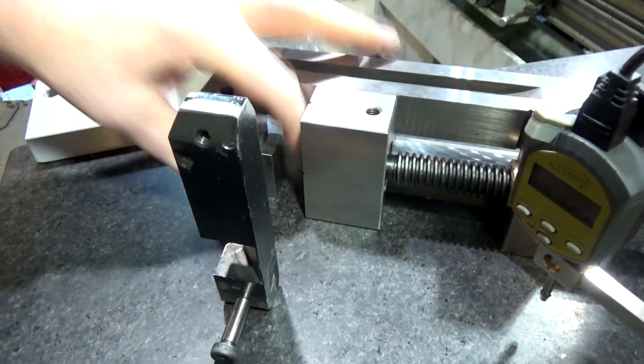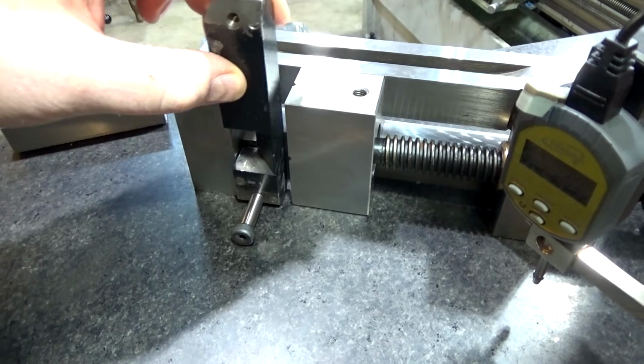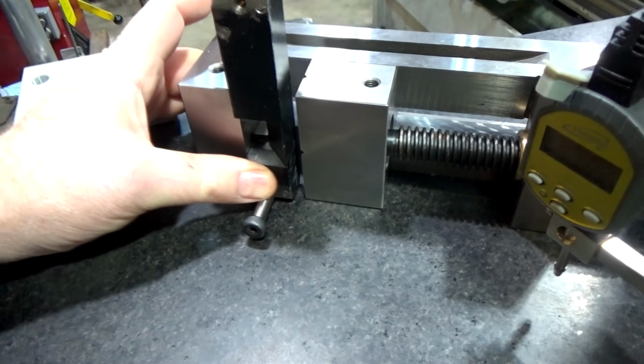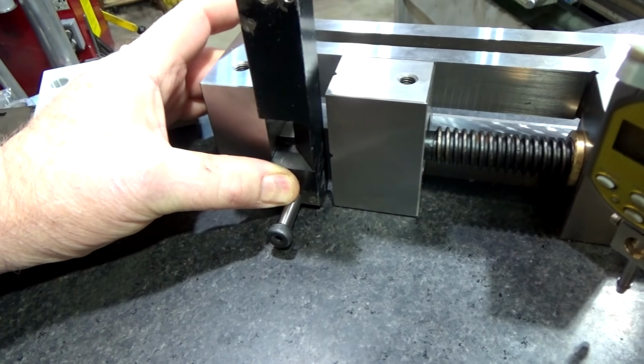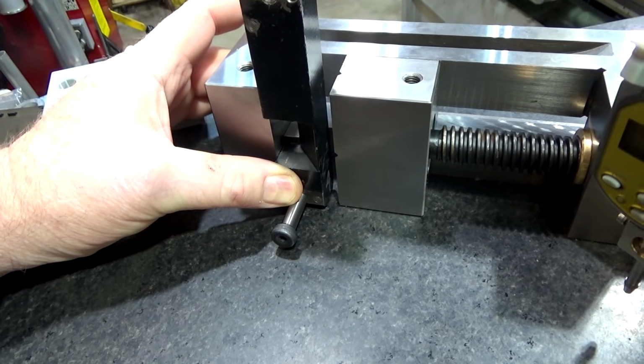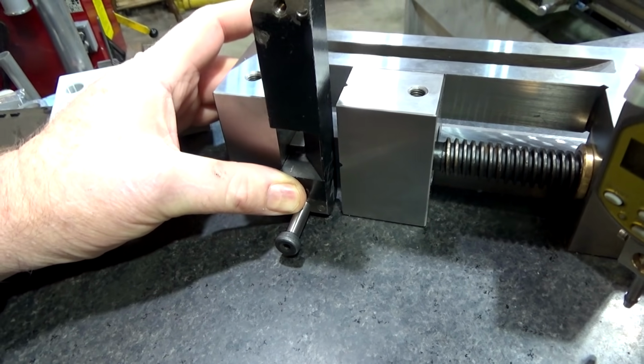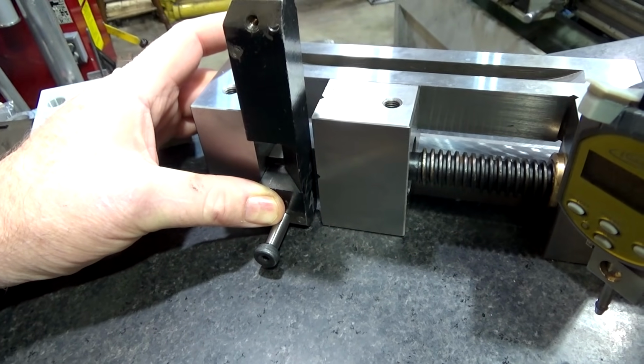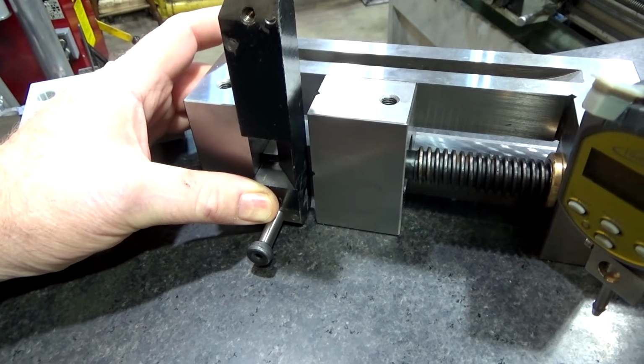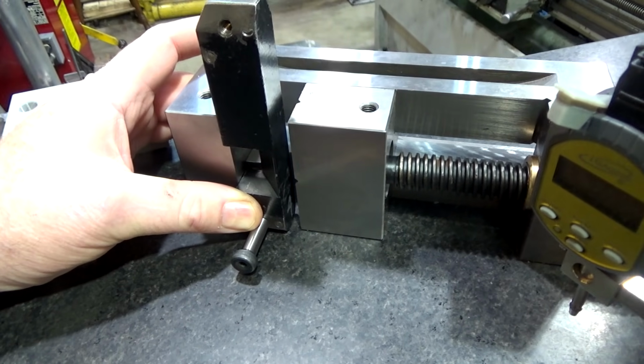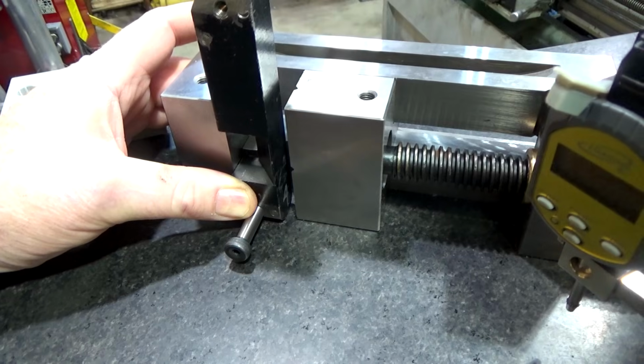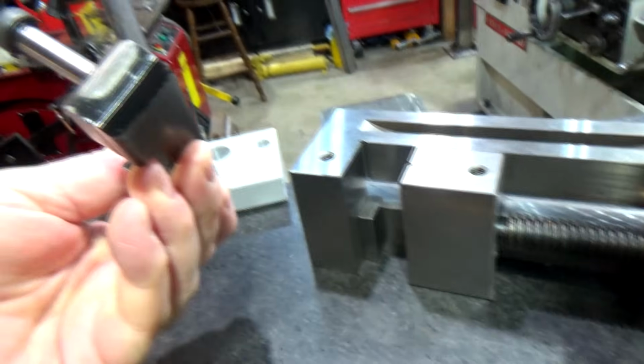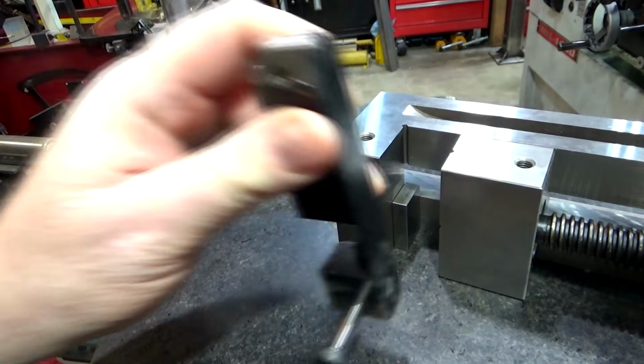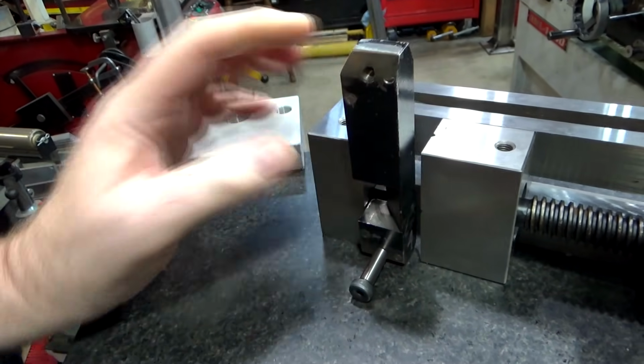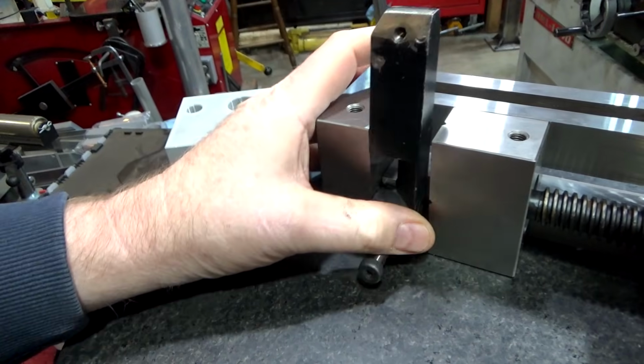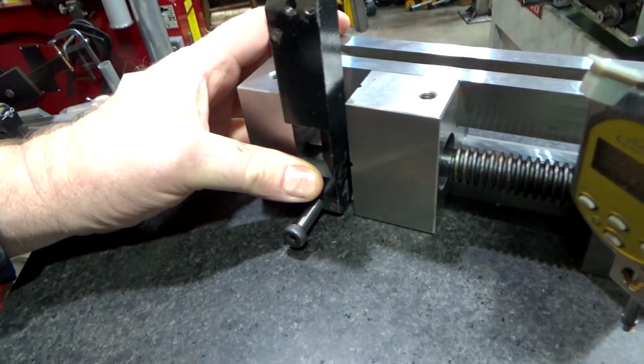So what I did was I took a gauge block off the bottom of the vise, and I held it tightly in here against the back and the side while I tightened it down, and then I was able to get repeatable measurements to within 1/1000th or 2 every time. Still not as precise as I would have liked, although this isn't that sort of project, but figuring out a way to do things repeatably is important to me, and this was only somewhat because, again, the bottoms of these things are hand ground, so they're actually sitting at an angle, all of them. And that's really problematic. You see, this doesn't even sit up on its own, even though that's a relatively flat edge.